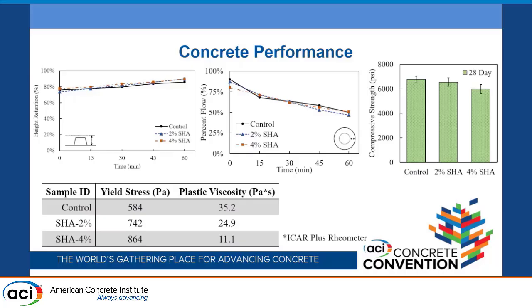Our plastic viscosity is a bit on the higher end. But importantly, with the inclusion of self-healing agent, since it's comparable to the particle size distribution of sand, we're starting to see an increase in yield stress and a decrease in plastic viscosity. Lastly, from compressive strength testing, we wanted to get a basic understanding of our mechanical performance.